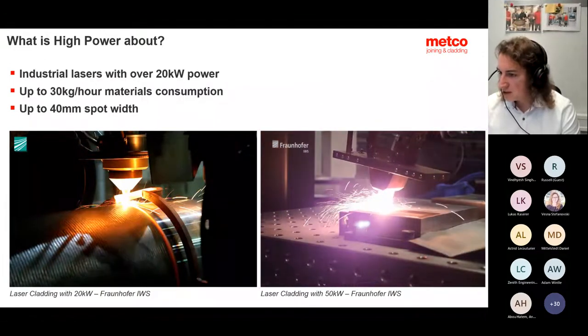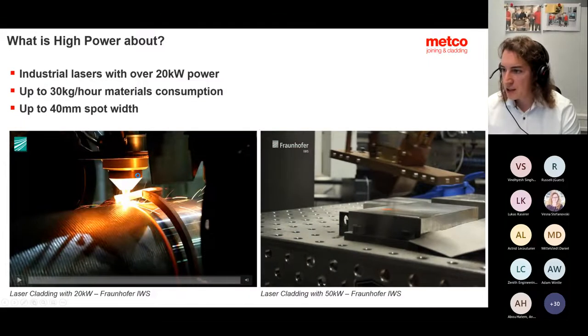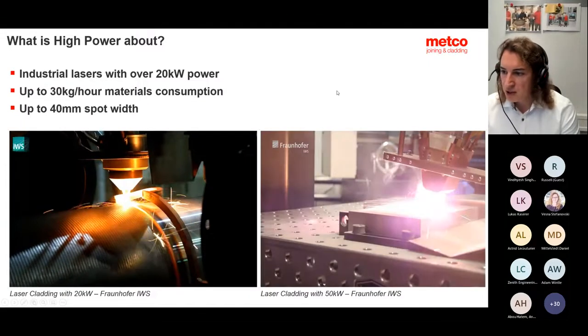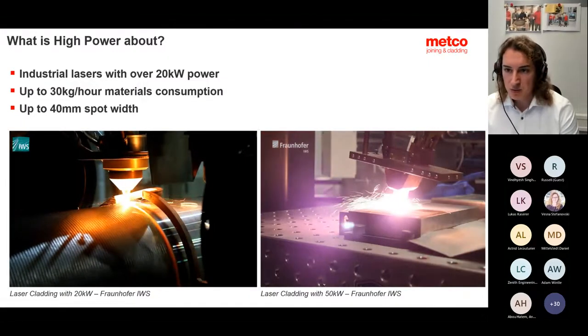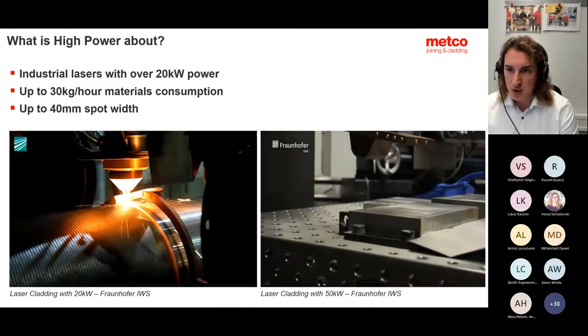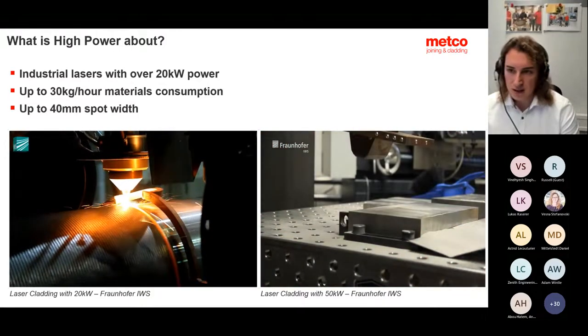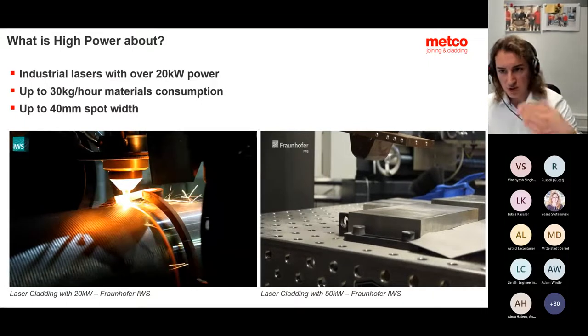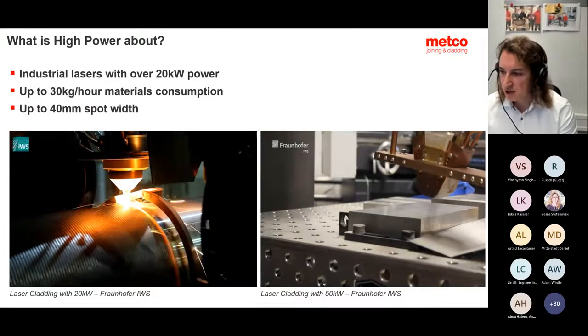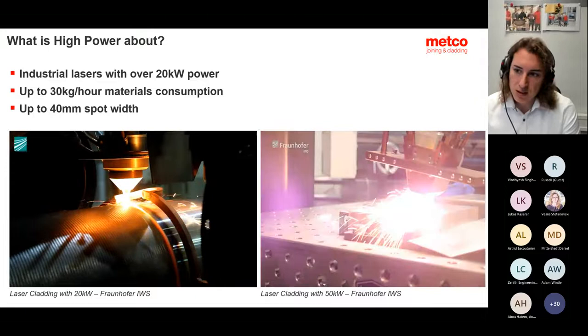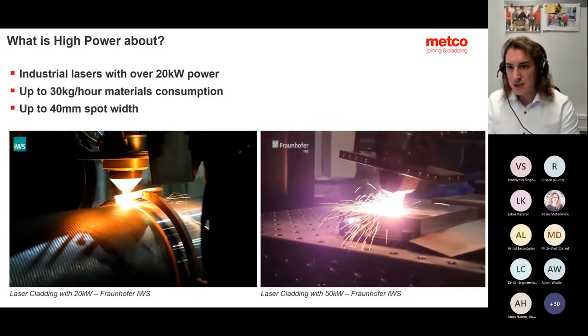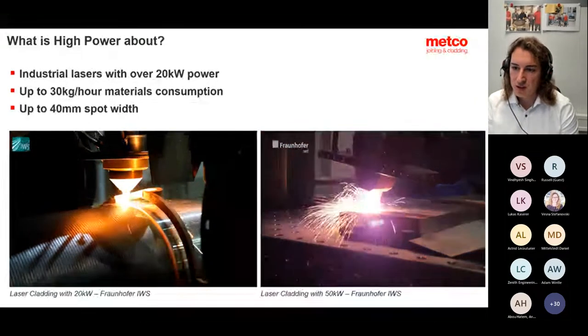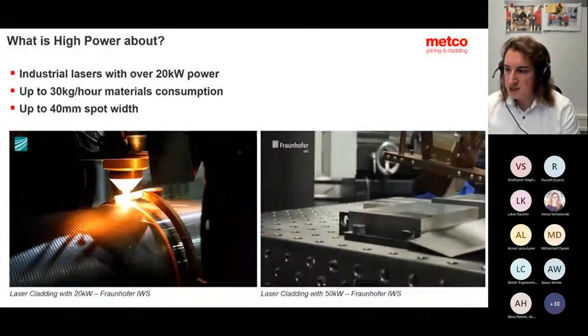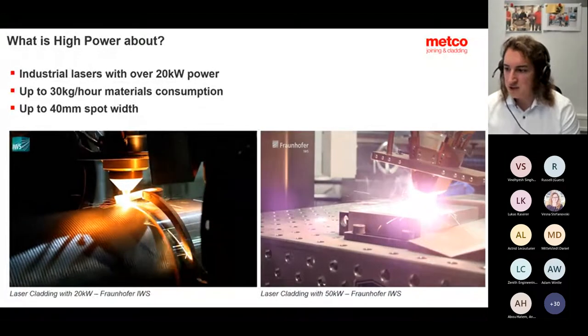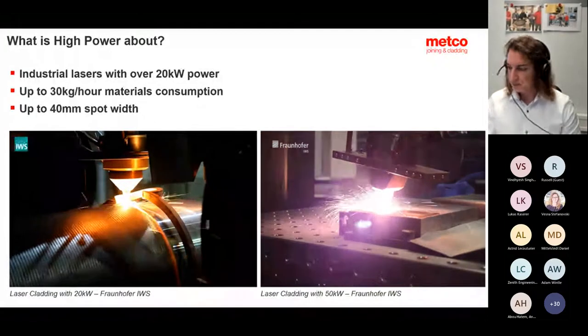And here are a couple of videos where you can see how the process takes place. High power is also working not only with a rectangular spot, you can work with coaxial nozzles, which also have extra cooling channels to withstand this type of heat input. You can also use inductive local surface heating, for example, to even further increase your feed rates and surface covering possibilities.